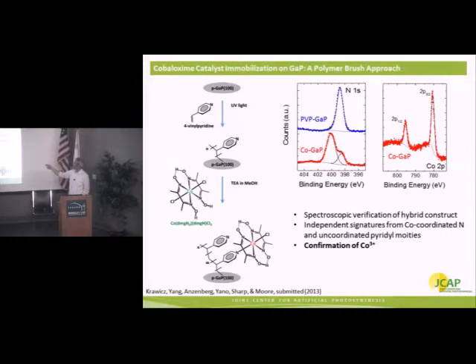Following growth of the polyvinyl pyridine layer, we see a single nitrogen signal associated with the nitrogen of the pyridine. After cobalt attachment, we see the emergence of a second peak. So we have still free pyridyl groups that have not reacted with cobalt. And the second peak, of larger intensity in this case, is actually from nitrogens that are coordinated to cobalt of the catalyst.